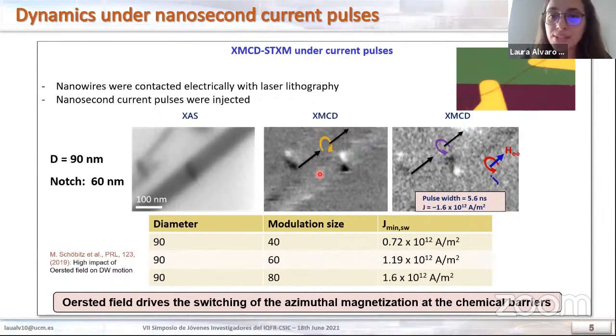So when we start with this initial state, we see that the curling of the chiral domain wall has a defined circulation, which is in this sense, and is white and black. And what happens is that when we apply a current pulse, the circulation of the curling is reversed. So if here it was white and black, now it's black and white. And it is reversed according to the circulation of the Oersted field that was applied. So this is a very important conclusion. That means that the Oersted field drives the switching of these chemical barriers.